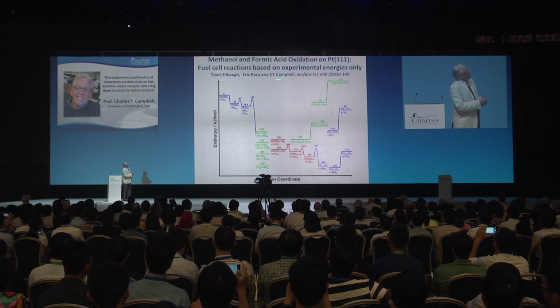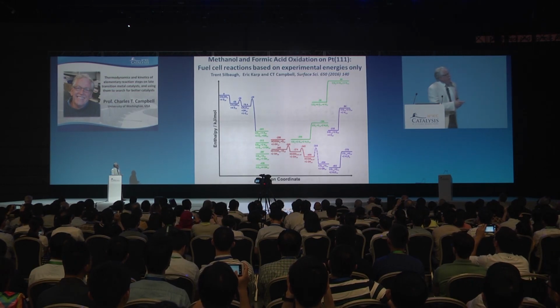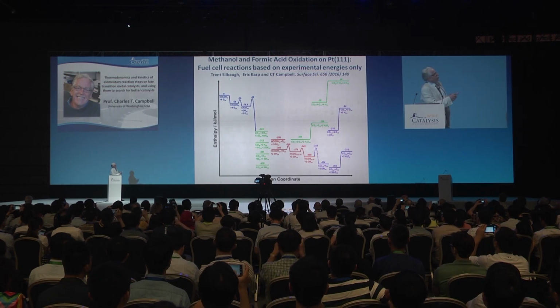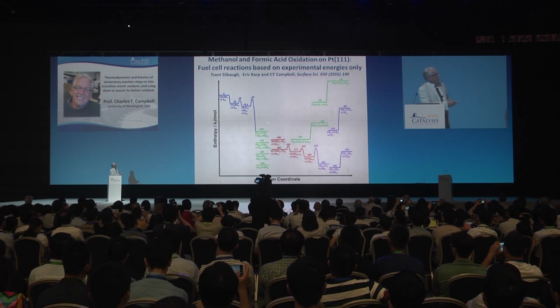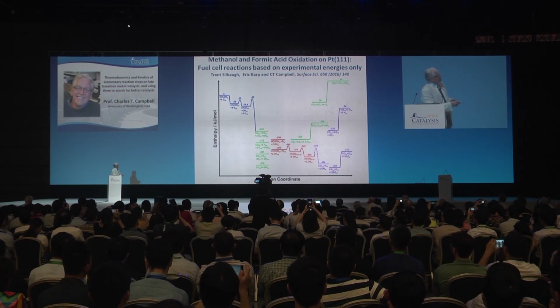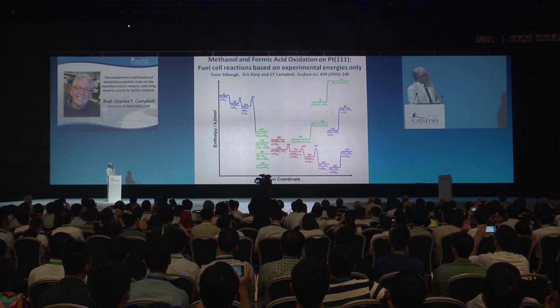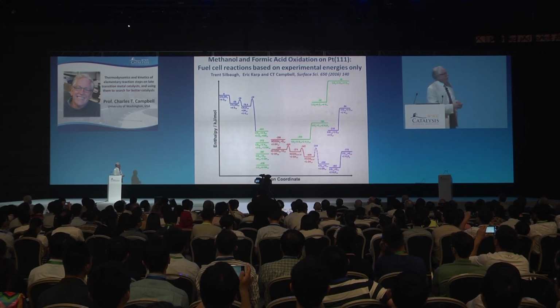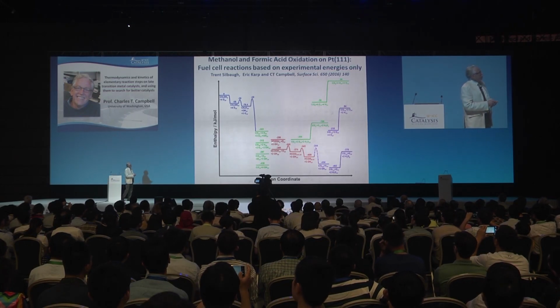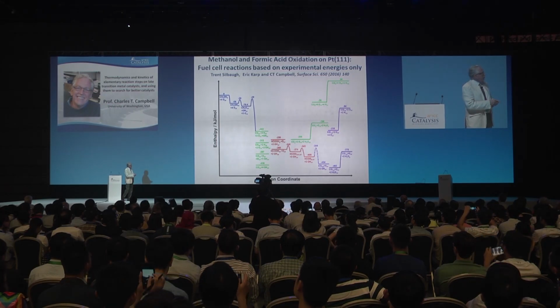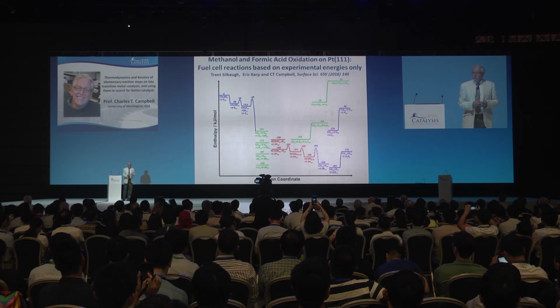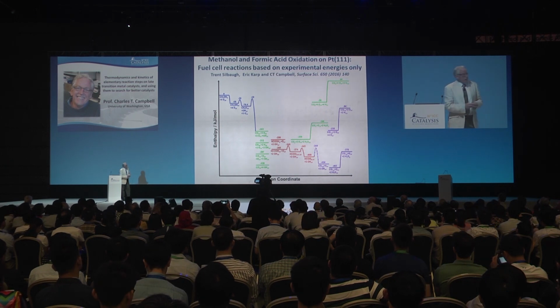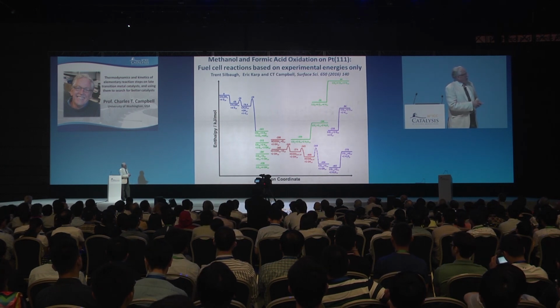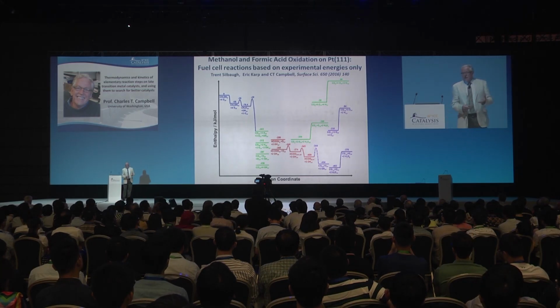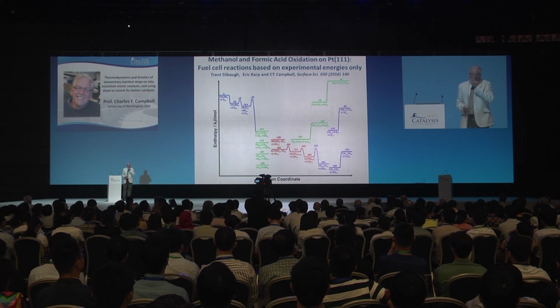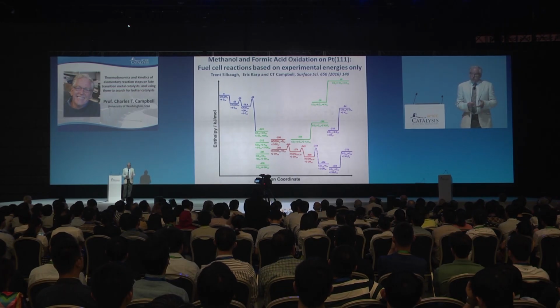And similarly, we can put together the energy diagram, assuming no solvent effects, for the important fuel cell reactions of formic acid and methanol oxidation, starting from methanol or formic acid gas to make CO2 and water. And when one puts together all of the energetics that we've measured for adsorbed intermediates, or other people have measured for some of the simpler ones, we can really get the full, if you like, energy diagram for those mechanisms. This is, I think, by far the most complicated energy diagram that's ever been done in catalysis from experimental measurements.